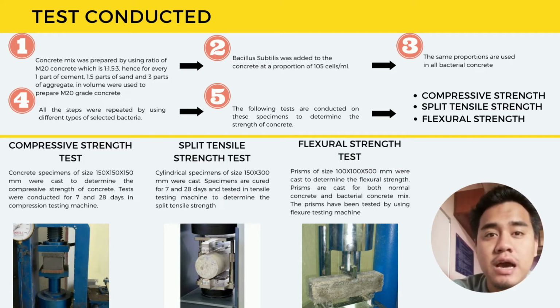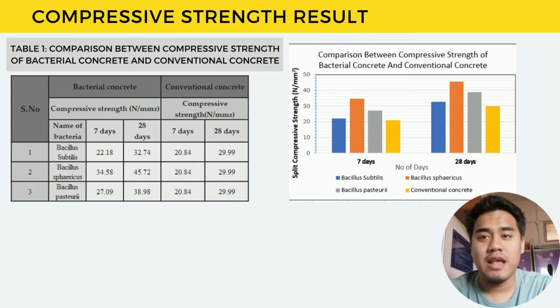The following tests are conducted on these specimens to determine the strength of concrete, which are compressive strength, split tensile strength, and flexural strength. Compressive strength result. Table 1 shows the comparison between compressive strength of bacterial concrete and conventional concrete. Three microbial materials were tested, which are Bacillus subtilis, Bacillus sphaericus, and Bacillus pasteurii, along with the conventional concrete. The result shows that Bacillus sphaericus has the highest compressive strength during 7 days and 28 days of curing, which are 34.58 Newton per millimeter square and 45.72 Newton per millimeter square respectively.